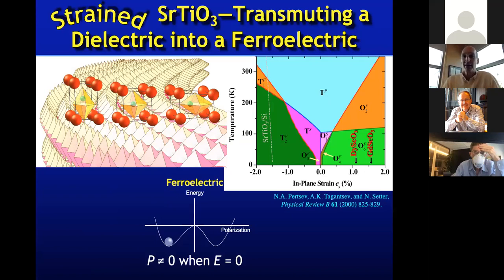The superscript F, on the other hand, means ferroelectric. So you see there are a lot of different Fs, and those Fs correspond, in this diagram, to different directions in which the polarization can lie. So for example, in biaxial tension, which is the right-hand side of the drawing here, which corresponds to this double well, it's favorable for the titanium to go off center, either to the left or to the right. When it does so, the titanium is a positive ion, so it's going to have a polarization when it goes off center to the left. That's going to be a polarization that's net to the left. Or equivalently, when it goes off to the right, it's going to be a polarization that's off to the right. So it's going to be an in-plane polarization. That's what's indicated here by this superscript F on the right side of the diagram with biaxial tension.